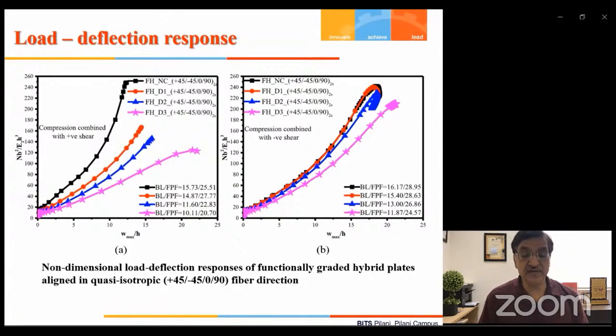In case of negative shear load combination, you see that the response of the plate with cutouts is very close to the plates without cutout, especially for small size cutouts. In case of cutouts of size D1, D2, D3, small, medium and big, we find a response for the cutout. The strength of the plate with the cutouts is lower than the strength of the plate without cutouts.